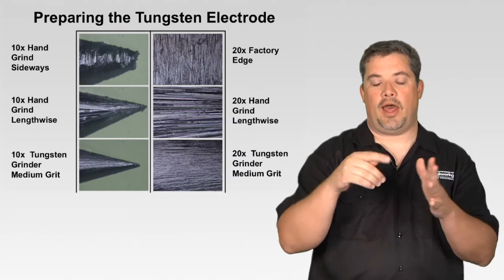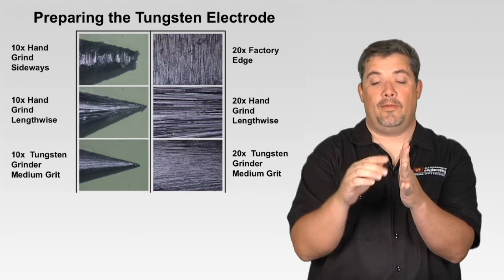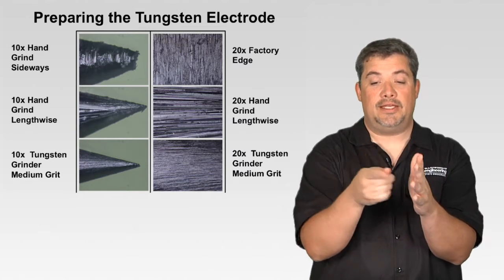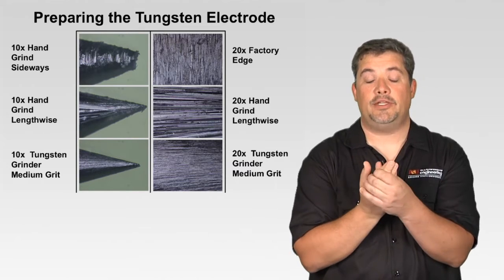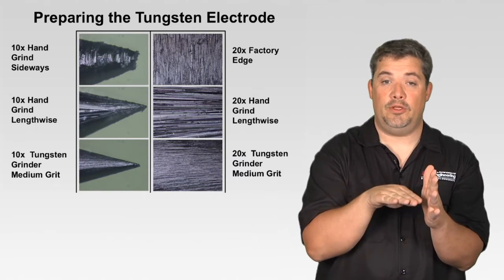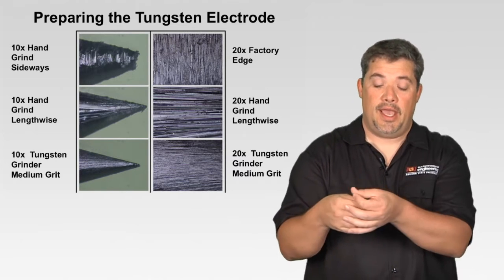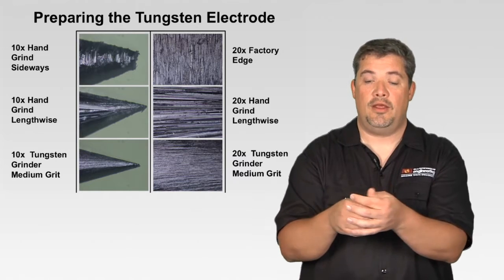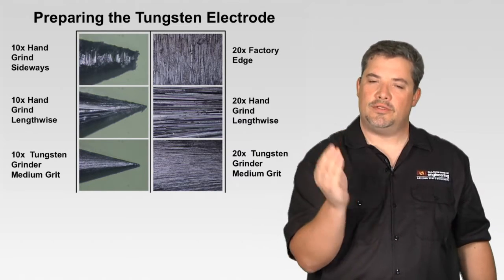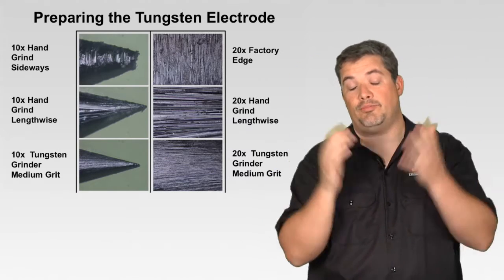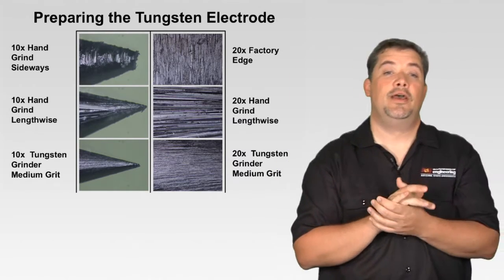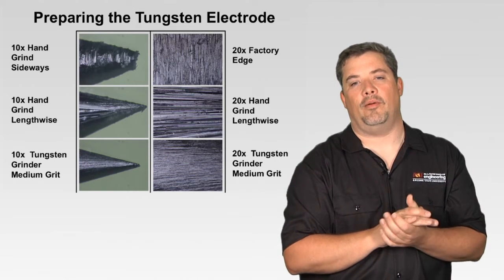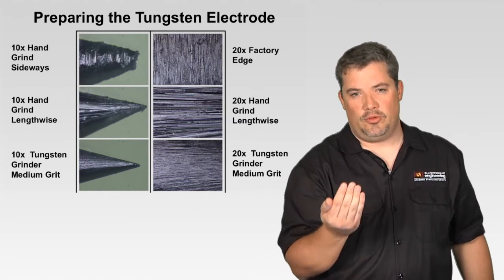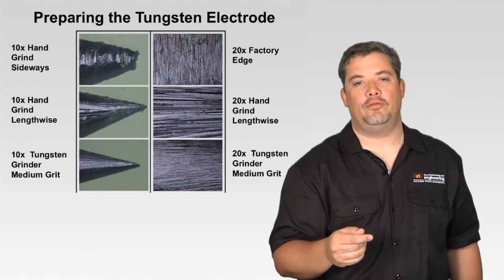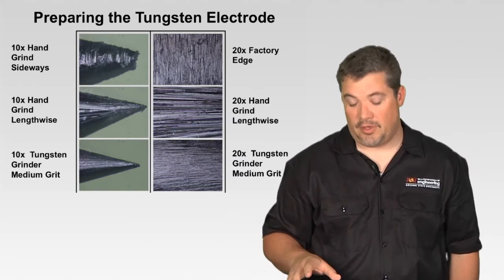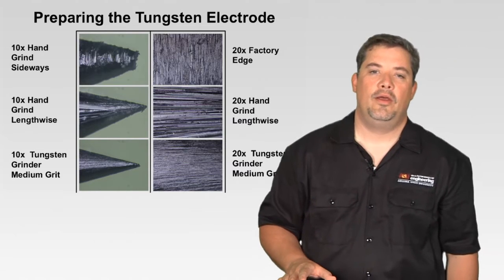One thing to note too, a lot of people sharpen with just a bench grinder with a fine wheel, and they start getting deep grooves on that wheel. Well, those deep grooves are very dangerous. You need to make sure you dress that wheel with a wheel dresser so that it's flat across all the time, and get in the habit of moving your tungsten side to side rather than creating those deep grooves, because those deep grooves could make that wheel actually shatter and just spit rocks all over your face and potentially into your eyes if you're not wearing proper safety precautions. So, smooth wheel. Don't let the grooves get in it, but better yet, just have a professional tungsten grinder to ensure that you're doing it right.